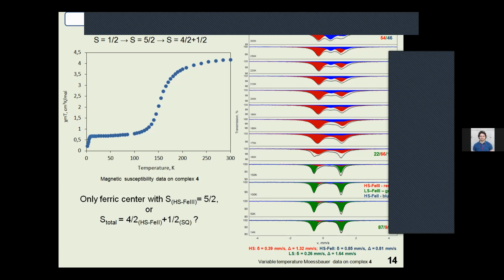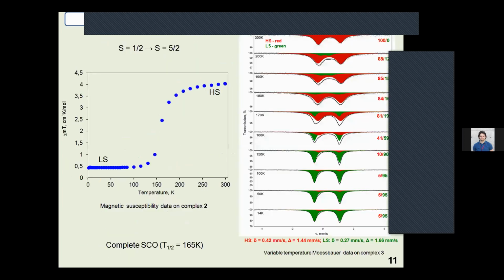Thank you for your question. Yes, in all these cases, from the first point of view, it's different. But in the case of compound 3, we have only 5% of molecules trapped in the high spin state. At the lowest temperatures, we see a small sharp decrease. As I know from the literature, in such compounds this sharp decrease is explained by the hyperfine splitting. And molecules trapped in the high spin state at these temperatures undergo a sharp decrease of the magnetic susceptibility.